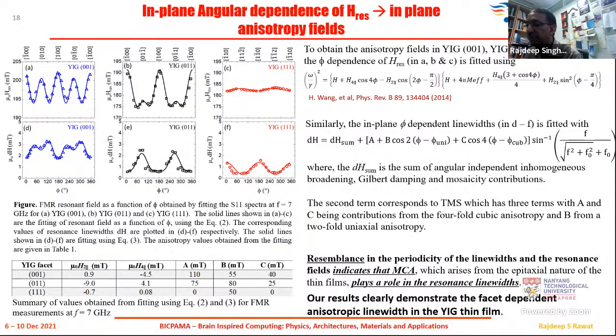So you see over here, once again, it's the same, but not in the 3-dimensional contour plots, but rather plotted as a function of an angle for the resonance field as well as the ΔH. You can also see, once again, it shows the 4-fold symmetry, the cubic anisotropy. This one predominantly shows the uniaxial 2-fold symmetry, but with some kink of 4-fold symmetry. And this one, hardly any variation. So we say almost like constant over there.